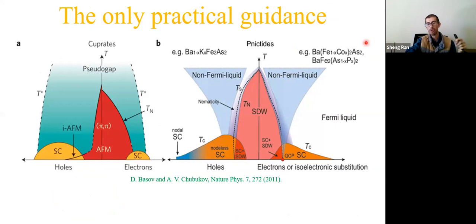The only guidance we have so far in the community is based on these two phase diagrams. On the left is a cuprate, on the right hand is iron pnictide. In both classes, the parent compound actually is not a superconductor. It has an antiferromagnetic ground state. Now, if somehow you can suppress antiferromagnetism by chemical substitution or by applied pressure, you have a lot of antiferromagnetic fluctuations, and it turns out that fluctuations can induce superconductivity, and those are unconventional. So a lot of people are working under this practical guidance.